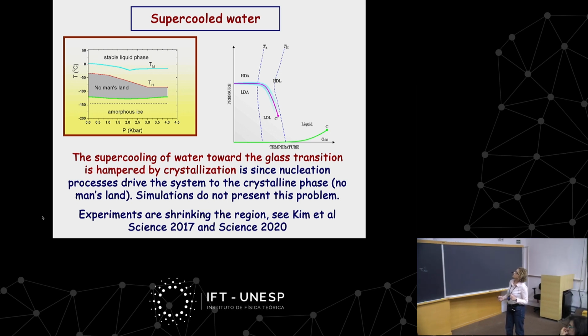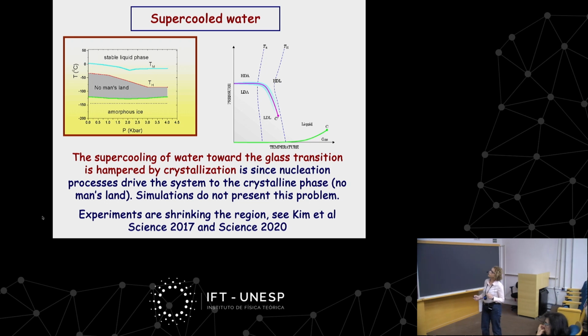So the supercooling of water toward the glass transition has some difficulties, because this is the water phase diagram in a region in which we have here the stable liquid. So this is the pressure, this is the temperature, this is the melting temperature. And in this yellow region below the melting, I can go with the experiments in the supercooled space with no problem. At a certain point, this is an experimental limit. We have homogeneous nucleation, and there is this part of the phase diagram in gray here, in which experiments